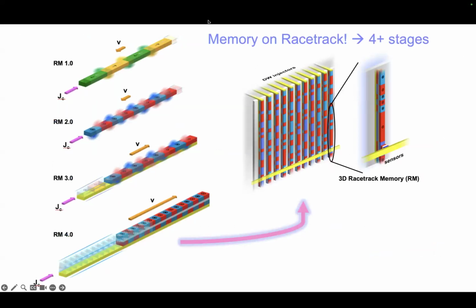We've evolved from, in racetrack version 1.0, simple, soft magnetic materials in which we use this spin transfer torque to move the domain walls, to the spin orbit torque to the spin transfer torque, the same thing, but in materials in which we've generated large magnetic anisotropies perpendicular to the racetrack so that we can shrink the size of the domain walls considerably, 100 times beyond the soft magnetic materials. And then finally, in racetrack version 3.0, we use spin orbit torques to manipulate the domain walls via the generation of spin currents through the spin Hall effect.